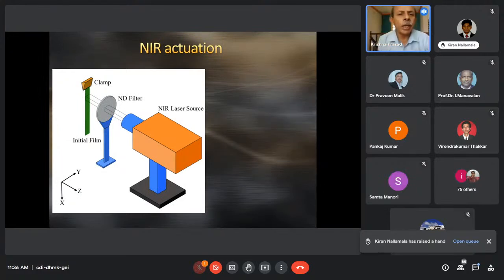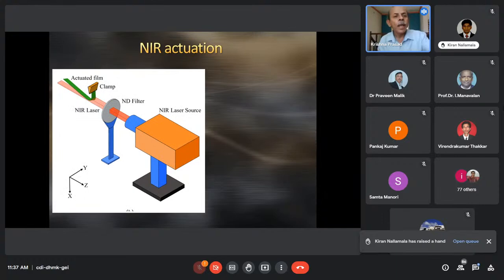Near-infrared actuation, wherein the green strip that you see is our actuator, which is created from the soft systems that we have fabricated. It is clamped to a solid support, and of course, just to control the intensity, we have an ND filter. The NIR beam, the near-infrared laser beam, falls on the actuator. That's the simple design that we have. When you impinge the laser onto these films, there's a significant actuation, and you see that the film bends significantly upon irradiation with the laser beam.